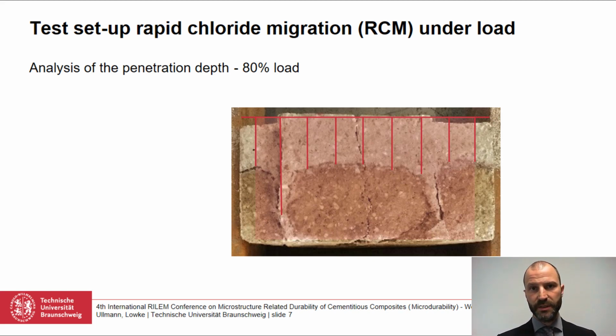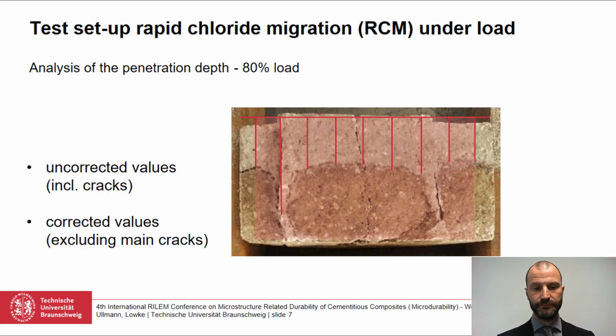And that is why we chose to differentiate when we do the analysis. Later on in this paper you will find some graphs that lead back to uncorrected values or to corrected values, and that means that we included or excluded these main cracked areas in the edge regions for all the 80% load specimen.